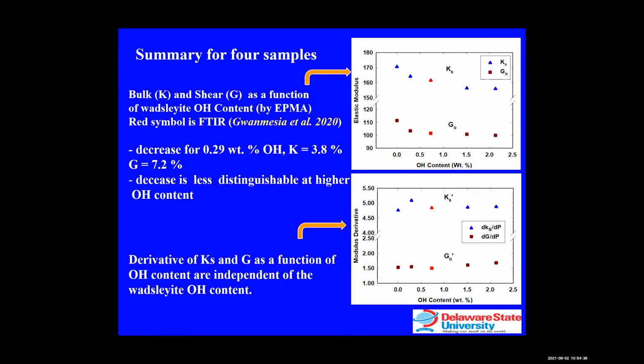And also we add the data for the anhydrous phase measured from the same study for comparison. As shown in the top right-hand corner, we first observe a significant drop in K and G of about 3.8% and 7.2% respectively by just adding 0.3 weight% of water. So the first drop is from adding 0.3 weight% water in the wadsleyite. And then as we further add water into the sample, the effect is not so dramatic, it's almost linear. That means that once we add up to maybe 0.3 weight%, any further addition of water does not seem to have a significant effect on the bulk and the shear modulus.